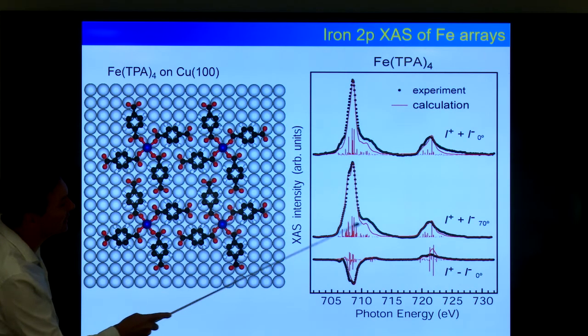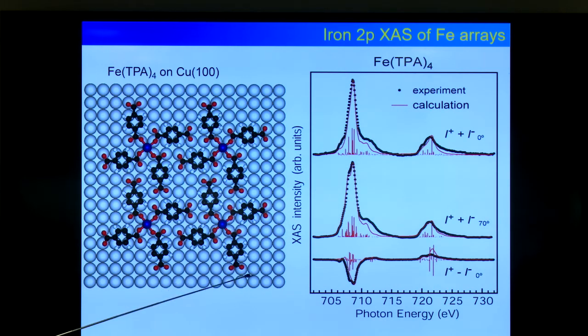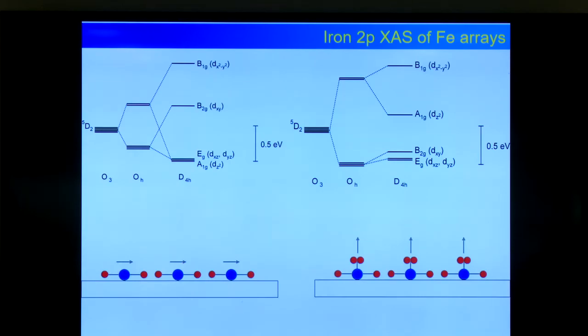So you can calculate your linear dichroism, and you get information about the orientation in space of the orbitals. And this is the circular dichroism at normal incidence, so you also get information on the orientation of your magnetic moment. And then by doing a lot of experiments at different angles, you get the final result on the orbital position.